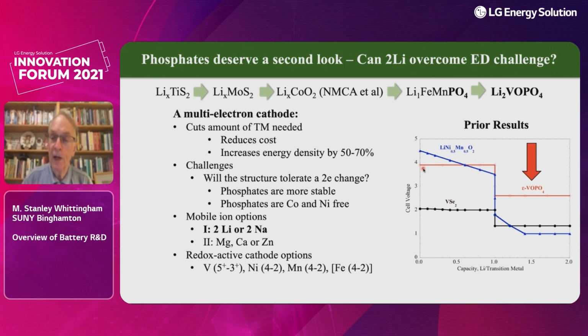In 2005, we showed that we could put 2 lithiums into this vanadium phosphate phase, one at just under 4 volts and the other one at 2.5 volts. And so this is the material I'm going to be talking about right now. The advantage of the phosphates: no nickel, no cobalt, and minimal release of oxygen, though the manganese phosphate can do that.